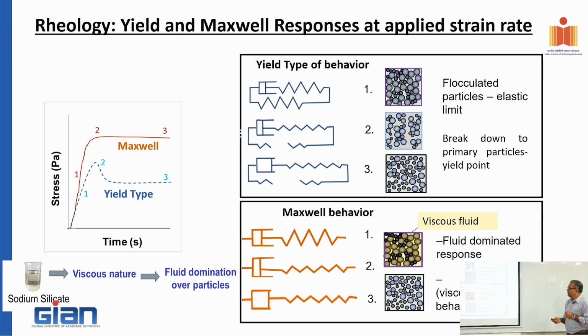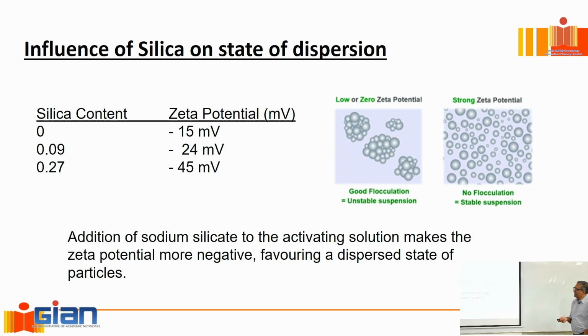And I'll show you what happens. The reason for that is when we add more and more silica into the solution, what we measure typically is the state of flocculation. How much are particles flocculated? And we measure this thing called the zeta potential. A zeta potential is something that will tell you how likely it is that these particles will agglomerate. If the zeta potential is more and more negative, that means you will see particles in an individually dispersed state. Whereas if the zeta potential starts going towards zero, the chances of flocculation are very high.